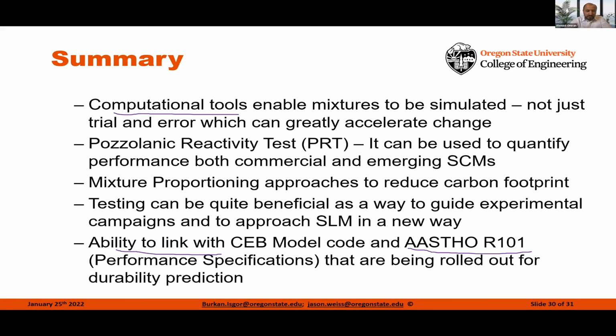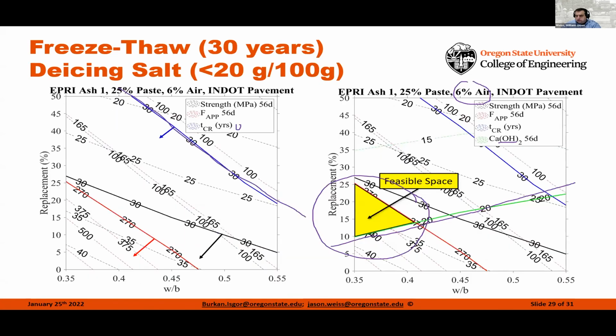The following question: what approach is being used to go from a degree of hydration and thermodynamic models to a time for comparison with the validation data sets like compressive strengths, etc.? Yeah, so we actually use the kinetic data. We have a lot of kinetic information that converts the rates of reaction into a time-based criteria. We use a lot of the Parrot and Killoh approach for the cements, but then we've added a lot of additional factors for the SCMs in the system.